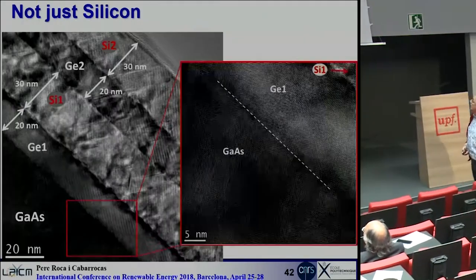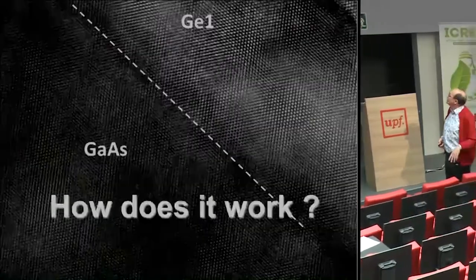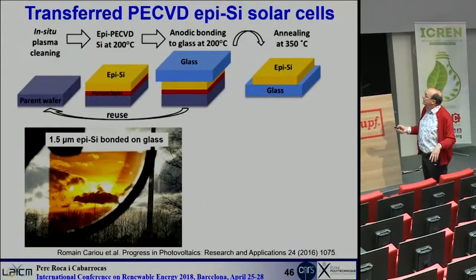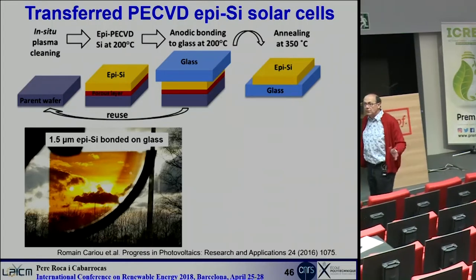And if you have this smart cut that you can tune, depending on the process conditions, then you can detach your epitaxial layer from the substrate. You can attach it to a glass substrate, and then you have your crystalline silicon wafer on glass, on plastic, on whatever you want.